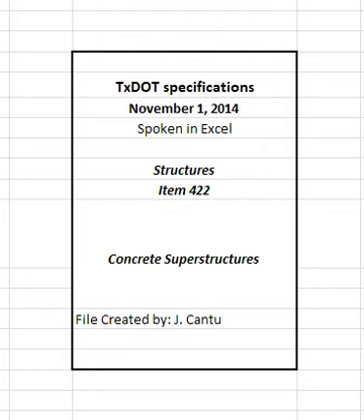Give a carpet drag, burlap drag, or broom finish to all concrete surfaces to be overlaid when the plans call for a concrete overlay (CO) to be placed on the slab, new construction. Saw grooving is not required in this case. Provide an average texture depth for the finish of approximately 0.035 inches with no individual test falling below 0.020 inches, unless otherwise shown on the plans.